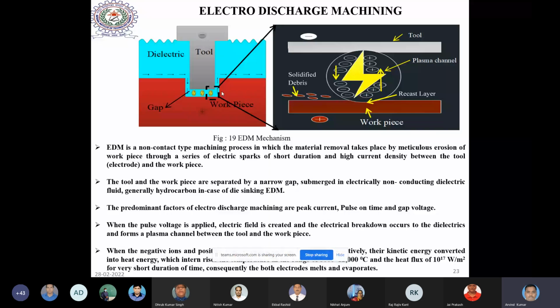Here, when the negatively charged ions strike, a huge amount of temperature increase occurs, ranging up to 22,000 degrees centigrade, and a heat flux of 10 to the power 17 watt per meter square for a very short duration of time. Subsequently both electrodes, meaning workpiece and tool, get melted and evaporated. So this is the beauty of electro discharge machining, that the hardness of the tool or material will not affect the machining process.